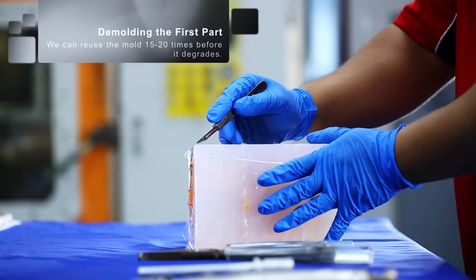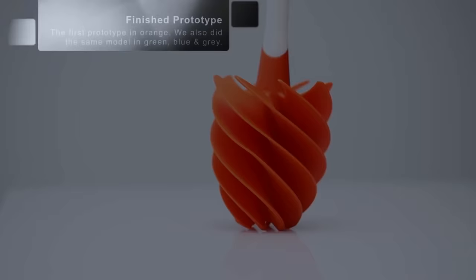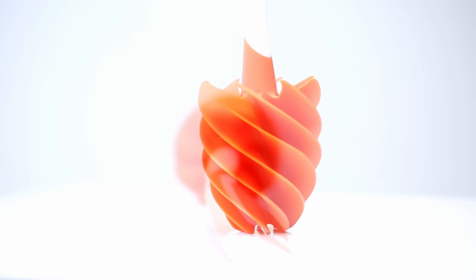After curing, we open the mould and voila! Once we cut off the gates and risers, we have a perfect copy of the original pattern. Silicone moulds can be used for up to about 15 to 20 castings before they need to get replaced. This is because they chemically break down when exposed to the resin, and the silicone turns white and hard and eventually crumbles.